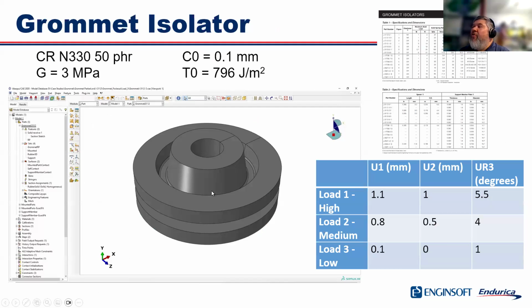So let's apply this to our grommet. Here are some material properties for the particular rubber that we've got. You can see I've got a shear stiffness of 3 megapascals, a precursor size of 100 microns, and a threshold of about 800 joules per meter squared. And I've got 3 load cases: a high, a medium, and a low load case that I want to model. And maybe I'm developing some specs for what the allowable loads are for this grommet.